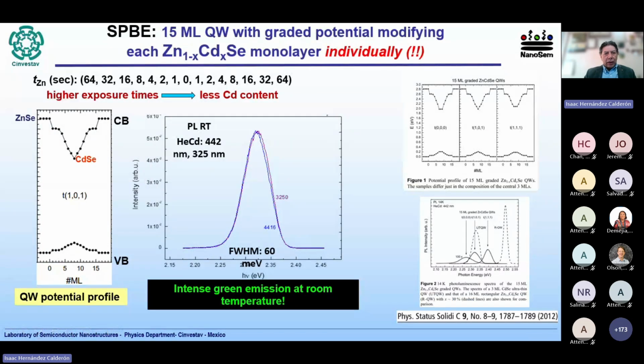Another very interesting and sophisticated example of a quantum well is one in which we grow a quantum well that has 15 monolayers of thickness, and we can tune each monolayer with a different cadmium composition. So here is the potential profile. It's related to the composition of the quantum well. And just by changing the exposure time to the zinc effusion cell, we can change the composition of each atomic layer of zinc cadmium selenide individually.